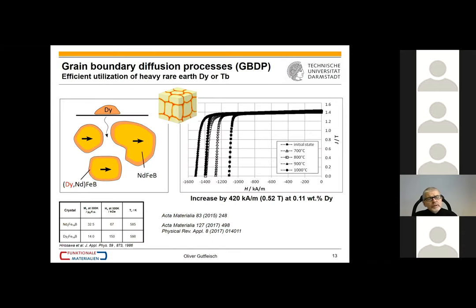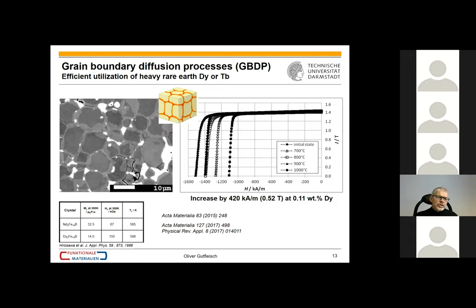So one effective way of making good use of the heavy rare earth elements: bottom left, you see the intrinsic properties. You see the well-known very high anisotropy field of the dysprosium iron boron 2-14-1 counterpart. We also see that magnetization drops due to the antiparallel coupling of dysprosium with the iron sublattice. But you see here that with the grain boundary diffusion process, we don't dilute dysprosium into the volume of the material, but we keep it at the grain boundary. So we don't suffer from this antiparallel coupling, and we keep a very high remanence, and with small amounts of dysprosium effectively distributed along and in the vicinity of the grain boundary phase, we can then bring up coercivity effectively. So we get such a shell-like structure. You see the light ring here, which represents the dysprosium enrichment.